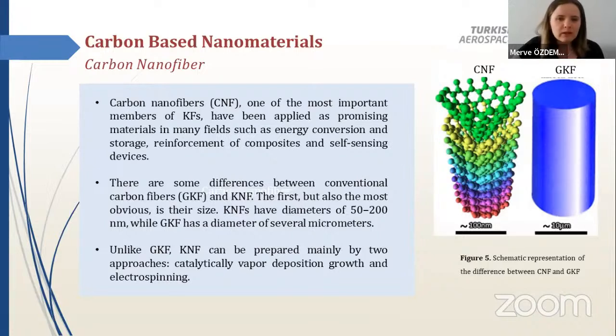Carbon nanofibers have diameters of 50 to 200 nanometers, while conventional carbon fiber has a diameter of several micrometers. Unlike conventional carbon fibers, carbon nanofiber can be prepared mainly by two approaches: catalytic vapor deposition growth and electrospinning. In figure 5, you can see the difference between carbon nanofiber and conventional carbon fiber.